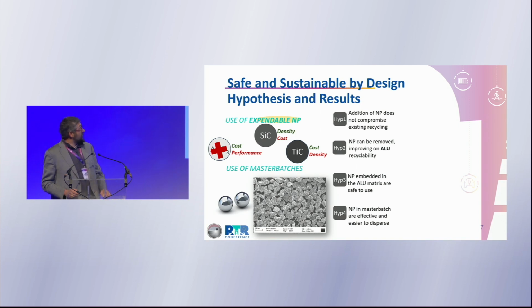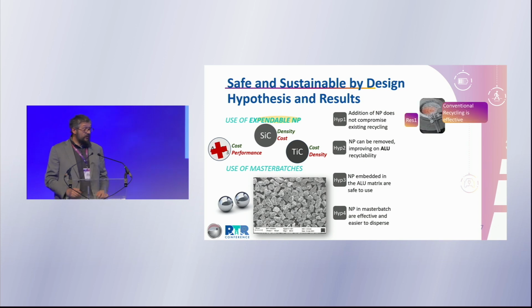Then we also want to verify that the embedded nanoparticles in master batches are safe to use throughout the different processes, and that the use of these master batches is effective in predispersing the nanoparticles. On the first point, we reached quite good results. Conventional recycling, we proved, is sufficient to remove the nanoparticles.